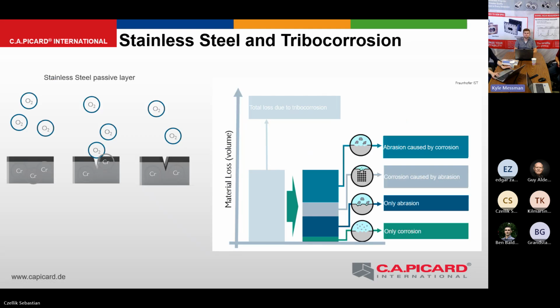Now I just want to show you why a stainless steel can rust. As I said before, it's building a passive layer. And this passive layer is built with chromium that is free in the matrix. So chromium and oxygen build a layer, so we have chromium oxide. When you scratch the layer, wherever, then it's broken. And normally it directly builds a new passive layer, so it's self-healing. But if you do that too often, it cannot heal anymore, and you will get rust at this point.